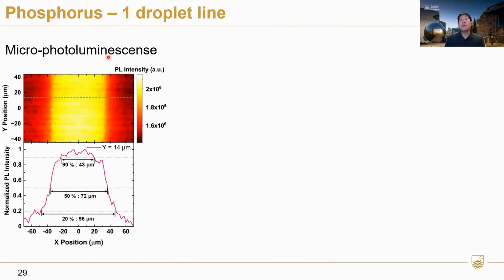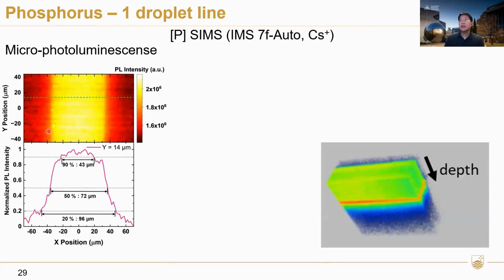Next, we do the same thing for phosphorus. The first thing is that the PL shows much straighter lines, similar to the optical images here. If we look at the SIMS image, again, it's also a very nice image. We can see this really sharp concentration red line here, showing that the concentration of phosphorus is higher over here. And this corresponds to the oxide interface. What it suggests is that there's a pile-up of phosphorus just within the polysilicon layer, just before the oxide layer. And this effect has also been reported by other research groups.